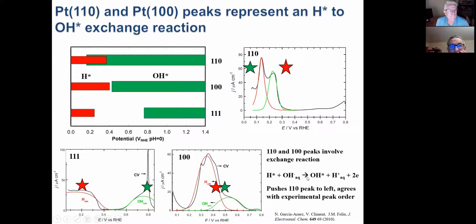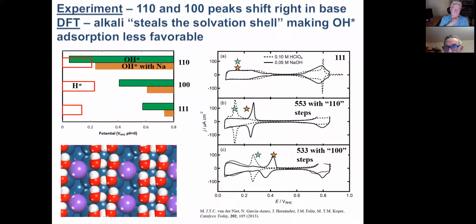So we've reinterpreted these peaks. I can't say we're the only people who've ever done this. This is Juan Feliu's group, detailed surface science, where they also suggested that though on 111, these peaks are separate, on 100 and 110, they're overlapping. But we can use now our DFT calculations to fit and explain this and back up this experimental explanation that sort of changes the textbook understanding of what's on the surface of platinum at different potentials.